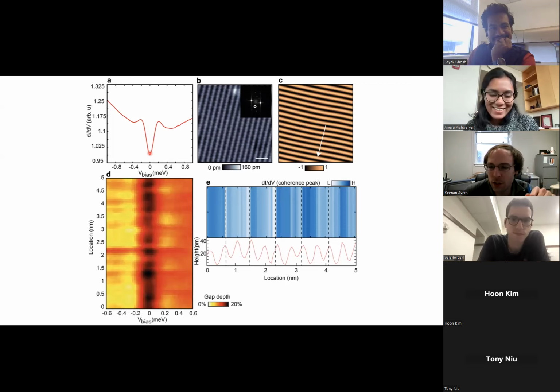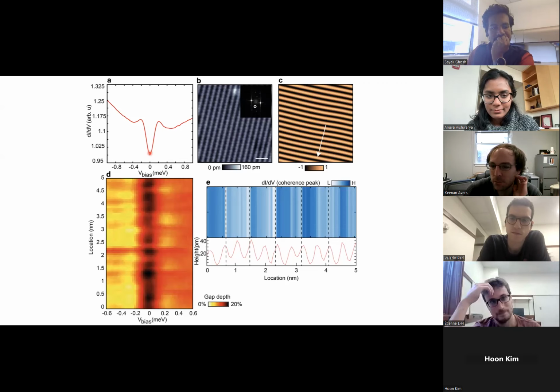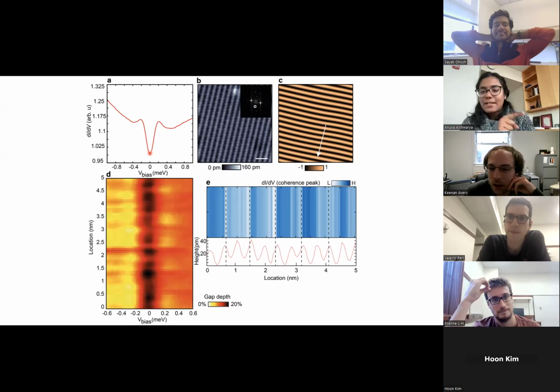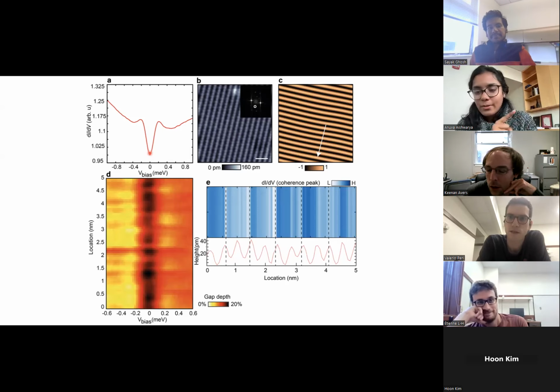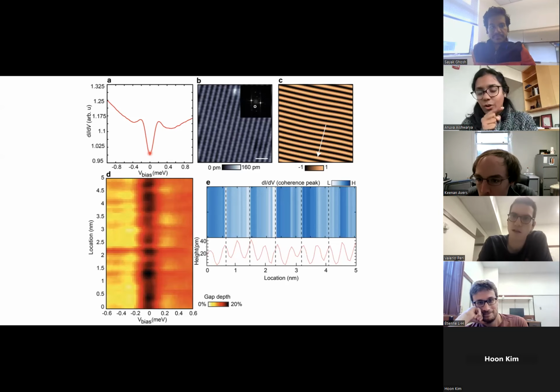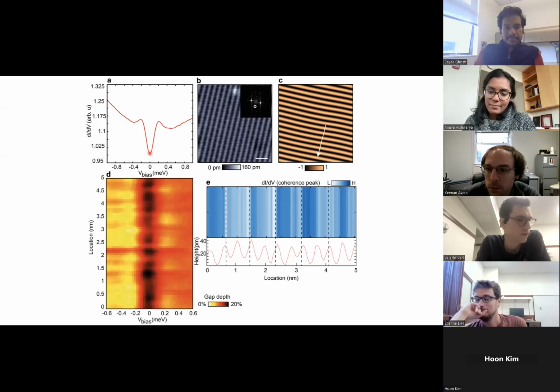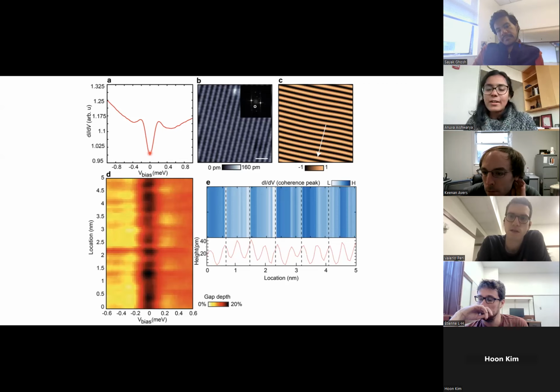Another silly question. Can you target individual vortices? I vaguely remember stories about possible Majorana fermions in the cores of P-wave vortices. I'm not sure if that's even been thought of. So the maps that I showed before are dislocations of the CDW. We don't know where the actual vortex of the superconductor is. There's some argument based on Ginzburg-Landau theory that you can find in the preprint of the paper, where we say that if you want to minimize energy, you will have these vortices at different locations. But it needs to be verified experimentally.